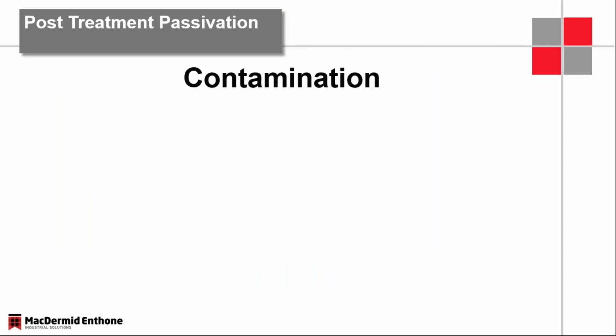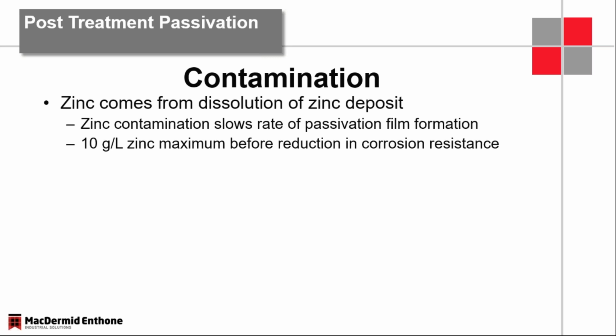Contamination is a really big point, and it goes to a couple of different avenues. Back in hexavalent chromate days, I remember checking zinc concentration in a hexavalent chromate a couple times, but it wasn't often, and it certainly wasn't every day. When the parts started to look poor, you would cut the bath or make a new one or make an adjustment, maybe increase the time, something like that. With trivalent Passivates, the zinc contamination in the Passivate film goes directly to corrosion resistance.